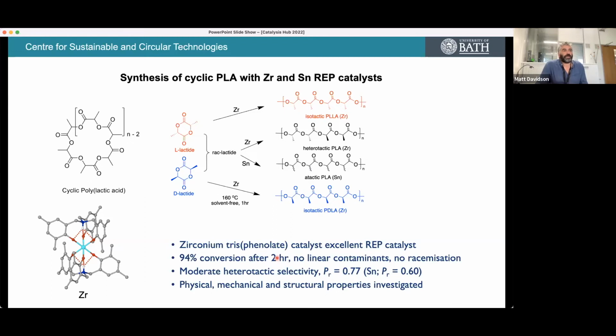So we get high conversions with these things. We get no observable linear contaminants. I'll show you on the next slide some evidence for that. We get no racemization, no transesterification. This is really rather similar to the results we were getting with the ring opening polymerization of these zirconium catalysts under industrial conditions. So they're very well controlled catalysts, and the really interesting thing is that they do give us stereoselectivity for these ring systems. I don't think any heterotactic selectivity has been reported for tin before, but we've looked at this in parallel with the zirconium work, and we do see some evidence for heterotactic selectivity for tin, but there's far more selectivity in the zirconium catalysts.